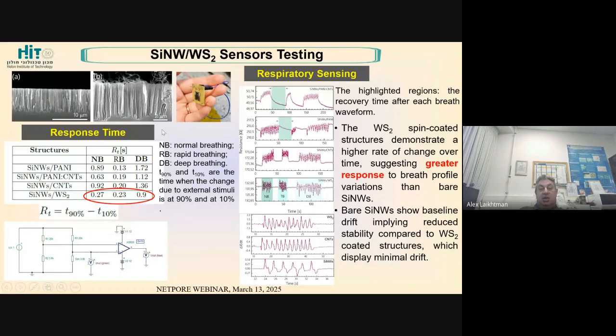And the response time, here is the explanation of what the response time is, has been measured for different types of nanowires. PANI means polyaniline. Polyaniline with carbon nanotubes, just carbon nanotubes, and WS2 nanotubes. As you can see, in nearly all cases, the response time for breathing in all regimes, or most regimes, for WS2 nanotubes was beneficial, was shorter than in the case of all other additives.